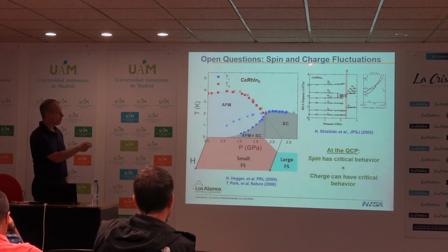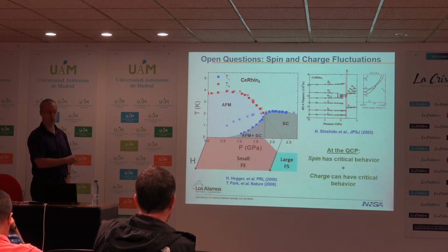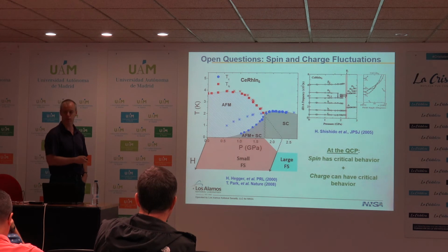So here are quantum oscillation measurements. This is the dHvA frequency, which is measuring the Fermi surface morphology. And as a function of pressure, it changes discontinuously at 2.3 GPa, which is precisely the point where the magnetism is suppressed to 0. And we have specific heat measurements as a function of field and pressure that really show that 2.3 GPa is the place where the magnetism is suppressed.